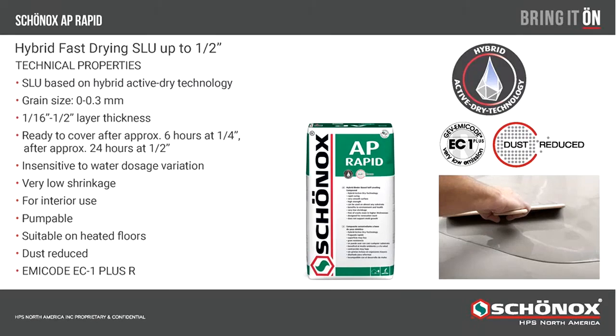Very low shrinkage on this material, so we can go over those critical substrates. We can go over the asbestos floor tile, the existing wood flooring, the sheet vinyl products, adhesive residues, cutback residues, those type products. We can actually pour this product over that with the primer system underneath. We are interior use only for this product. It is pumpable. We are suitable for underfloor heating systems.